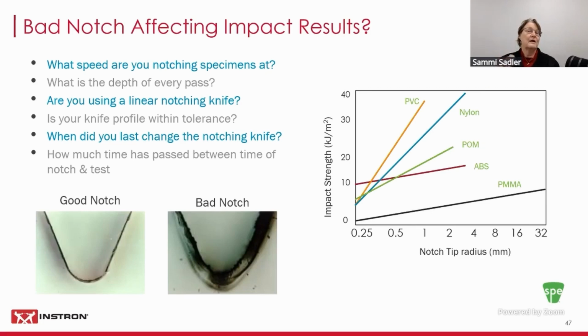So now whereas the standard defines how much material will be left below the notch, since we've melted material, that value is going to change. Things to look at with your notching is what speed are you notching the material at? How much material are you removing every time you pass either the blade or the saw over it? Are you doing a linear notch, or are you doing a single tooth saw blade?